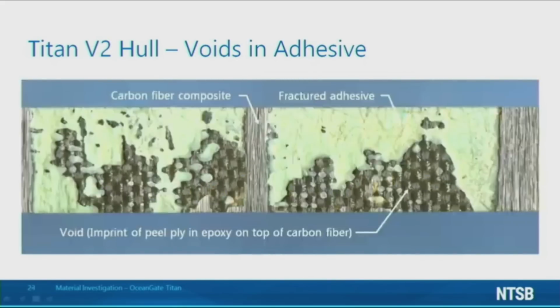3 distinct regions were seen on the fracture surface. The green regions are fractured adhesive. The vertical linear features are fractures through the carbon fiber composite. The checkerboard-like regions are thin layers of hardened epoxy that are above the carbon fiber composite but beneath the adhesive. The checkerboard patterns were left behind by the peel ply that was used during the curing process and then subsequently removed. The areas where you see this pattern were associated with the voids.